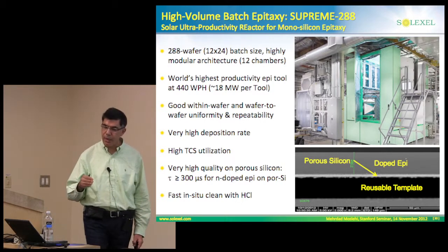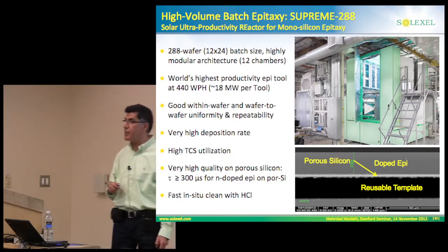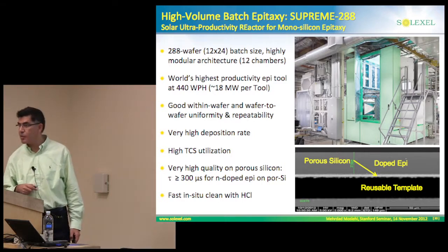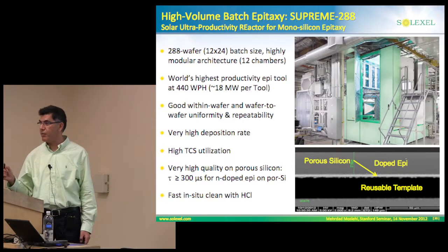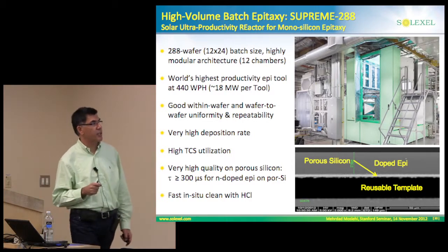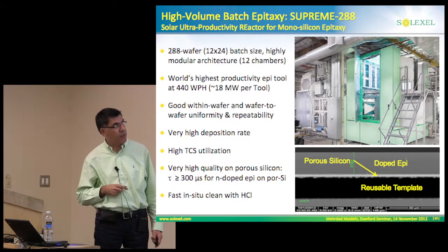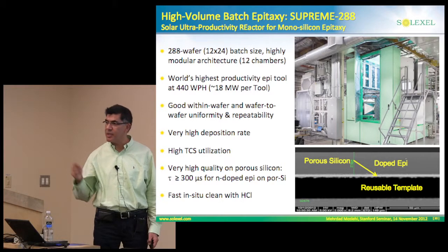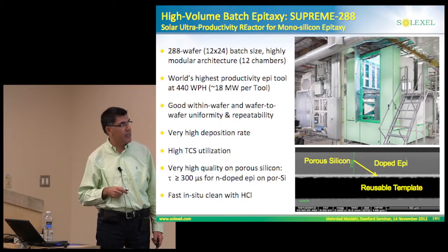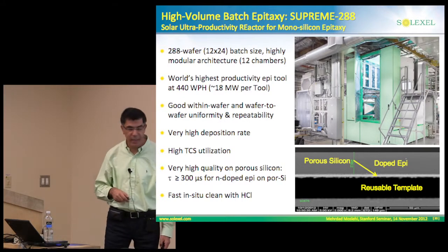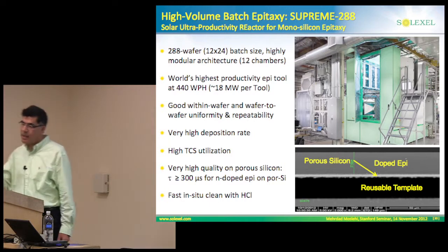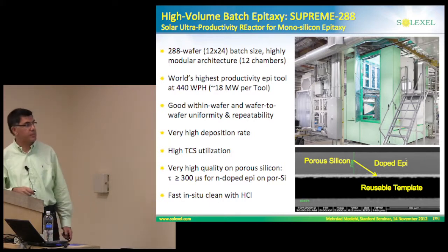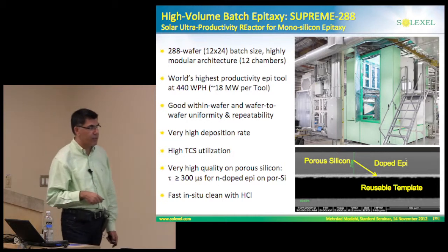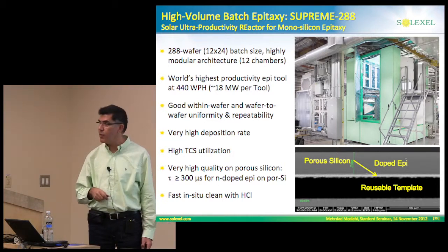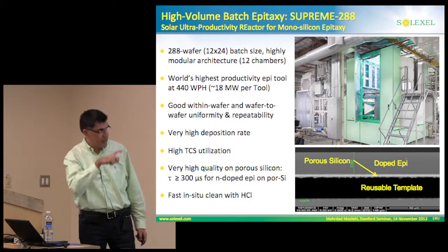For our technology, it provides about 440 wafers per hour, and this translates to about 18 megawatts of cell production per tool. We achieve good uniformity and repeatability, very high deposition rates on the order of 2.5 microns per minute, and very high TCS utilization, very high quality of doped N-type silicon on porous silicon. So this is very important. We consistently get over 300 microseconds for our N-doped absorber that we deposit with this tool.